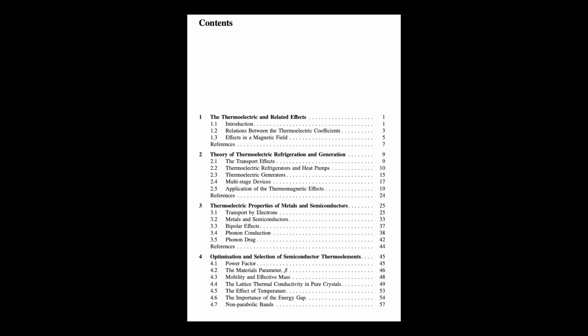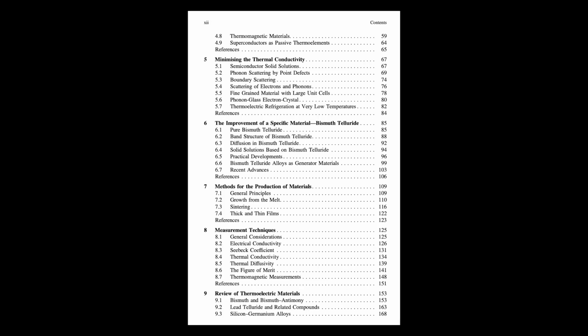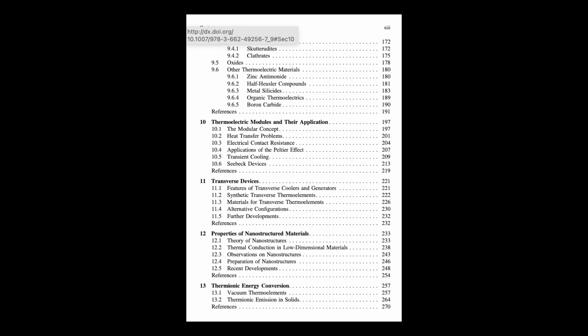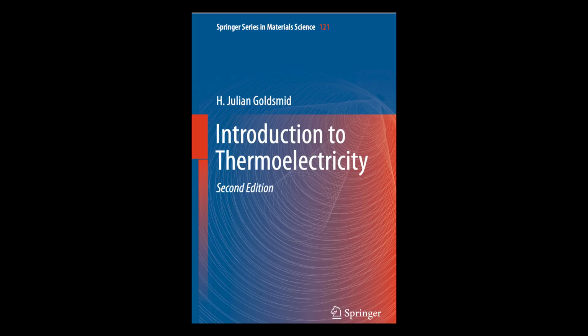Makes sense. Finally, in this section, cooling down to very low temperatures, what are the hurdles using thermoelectrics way down there? Yeah, cryogenic thermoelectric cooling, like below liquid helium temps. That's tough. The main problem is the figure of merit, ZT, usually tanks at very low temperatures. Things like mobility, thermal conductivity, they all change drastically. But there's still some interest in specialized semiconductor elements. The book mentions that materials with high Debye temperatures might actually be better down there, which is kind of the opposite of what you often want at higher temps. Effective mass, scattering mechanisms, they all become super critical, getting practical cooling way down there. Still a really hard problem.